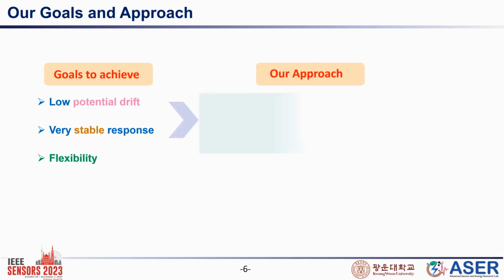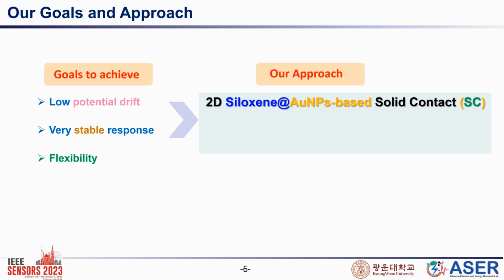So our approach is like that. We have considered a siloxene based material. Siloxene is a 2D material which has good electrical conductivity as well as high surface area. And we have considered another nanomaterial, metallic nanoparticles, gold nanoparticles actually. So why gold nanoparticles? Gold nanoparticles favor the formation of a double layer capacitance with a high surface area. So that's why we have included gold nanoparticles with siloxene. Siloxene itself is very conductive and has a very good surface area, and in parallel, the gold nanoparticles also enhance the surface area. Also, they increase the ion to electron transition. So, considering all 3 conditions, we have selected a 2D-Siloxene and gold nanoparticle based nanocomposite as the solid contact layer in this work.